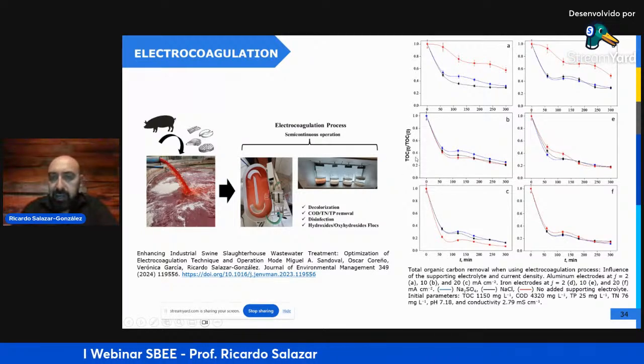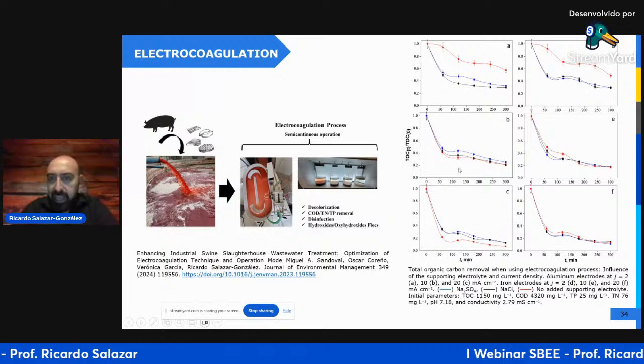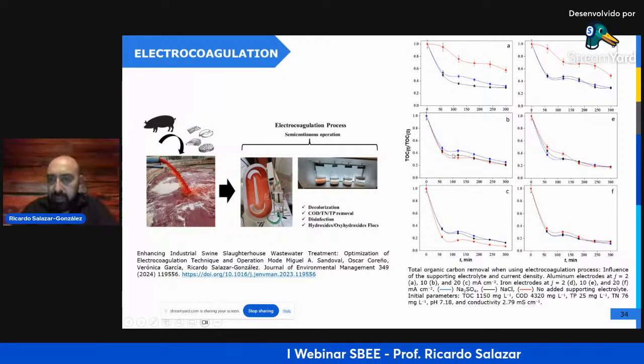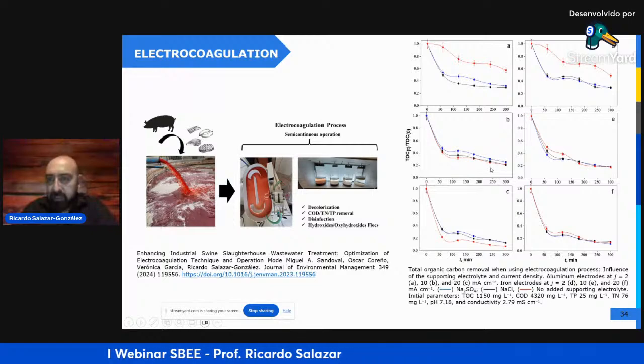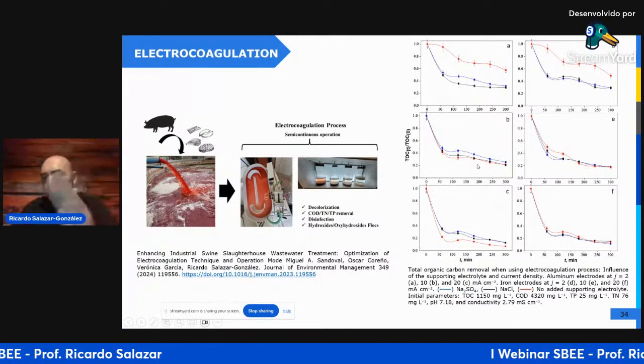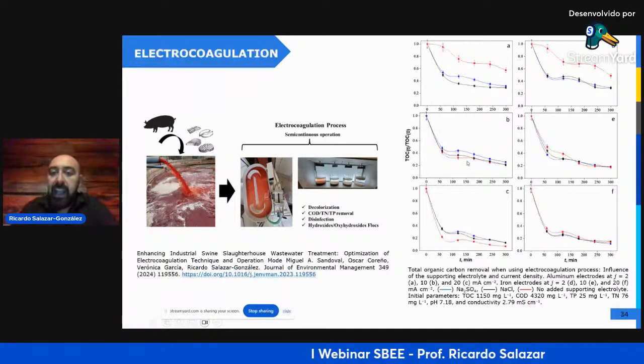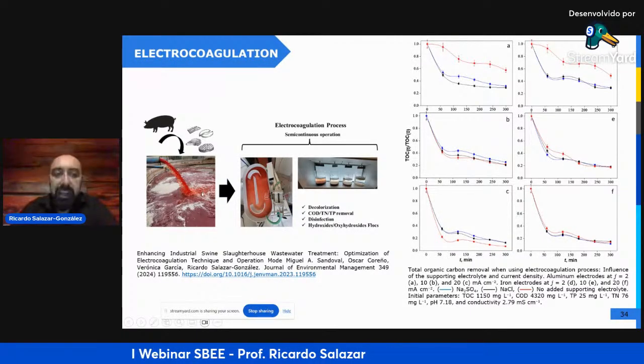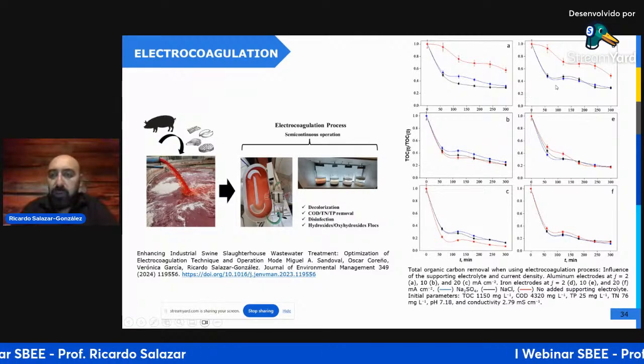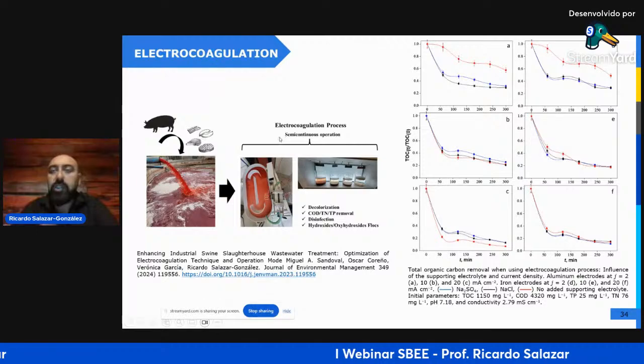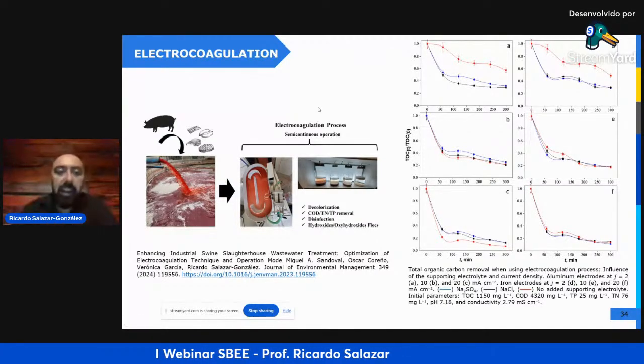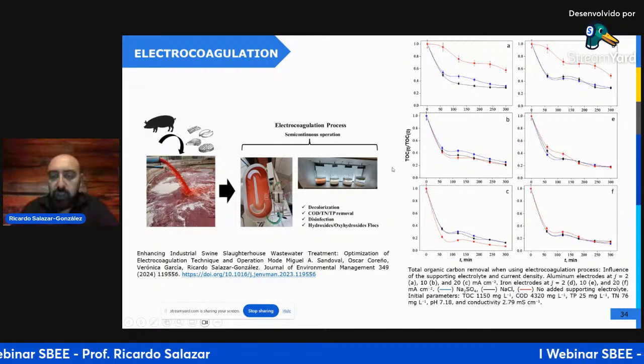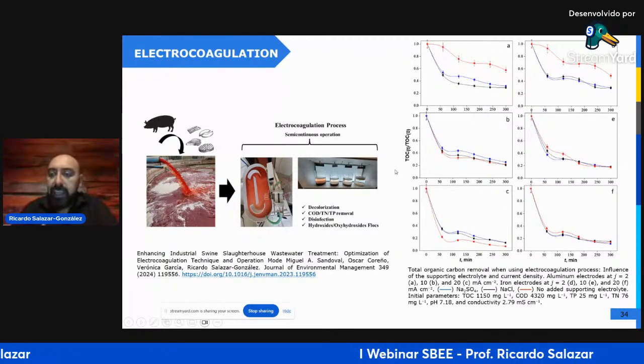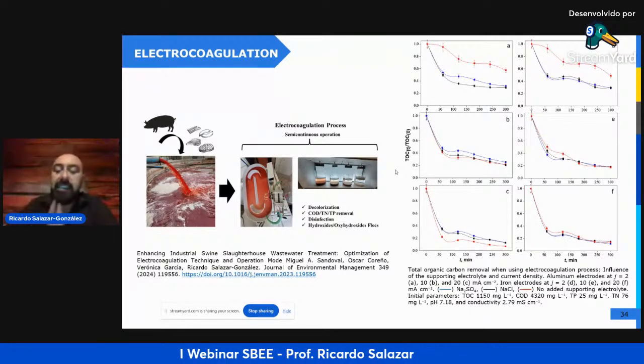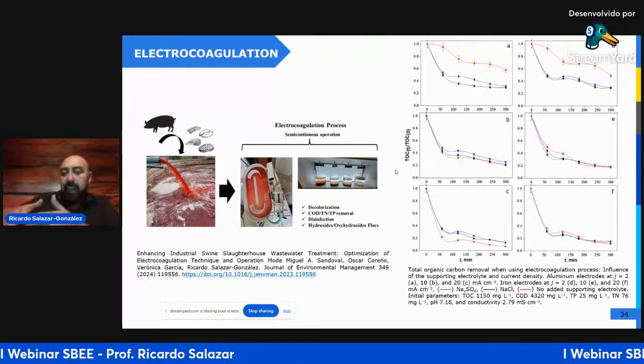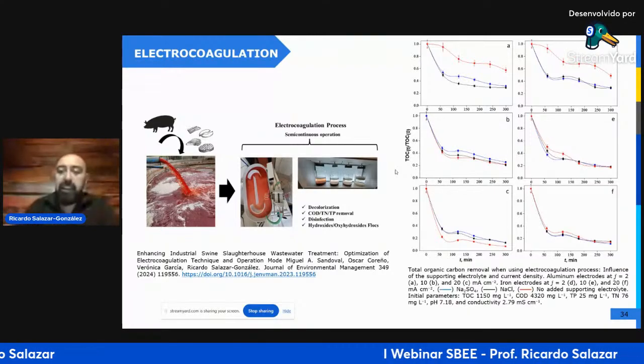And here you can see the TOC decay of the water. The total organic carbon remaining in the water is close to 20%. We can remove almost 80% from the wastewater. And the electrocoagulation process can be applied without the addition of supporting electrolyte. So you can use the conductivity or the salinity of the real wastewater without adding supporting electrolyte. But if we want to decrease the electrolysis time or increase the efficiency, we can add salt to the solution.